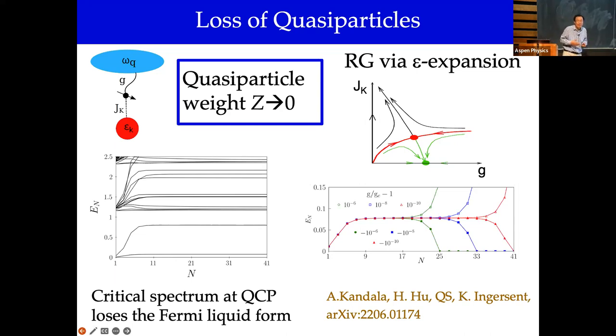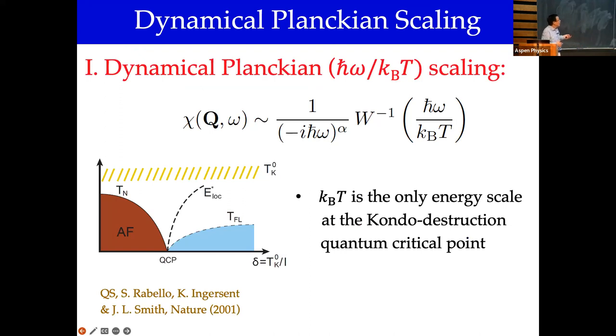As a result, there are a number of important consequences which can be confronted with experiment. The first one we looked at is dynamics, which the condensed matter experimentalists can probe. It's the spin dynamics. You can go to facilities for inelastic neutron scattering and measure the imaginary part of the dynamical spin susceptibility. And in fact, that was the first puzzle: why these data were showing almost blackbody-radiation-type Planckian scaling, ħω combining with k_B T, and also some fractional exponent. This comes out because this fixed point, like the Fermi liquid fixed point, is, in the fixed point language, interacting as opposed to Gaussian.